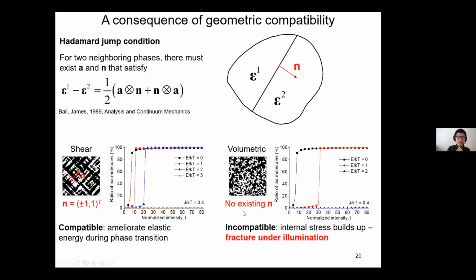mathematically you can prove you cannot find any existing n across these different domains based on the photo strains. That means you have to deform this material, right? To induce the elastic strains that make them compatible. That also means you need to induce large internal stress in the material. That explains why these materials, in this case, are easier to fracture on illumination.